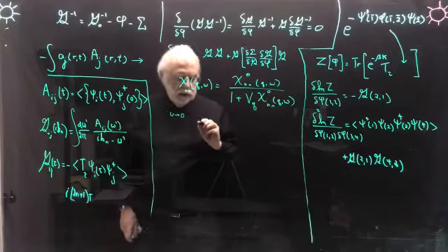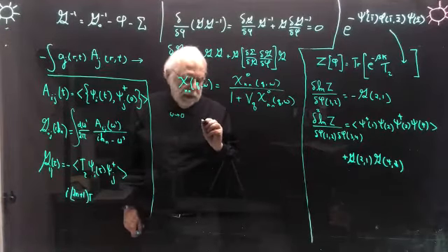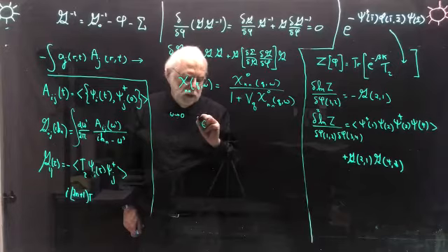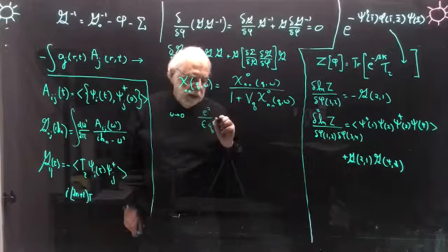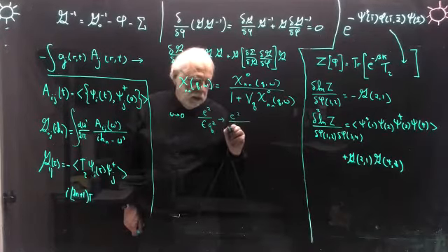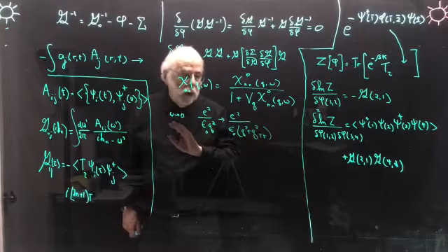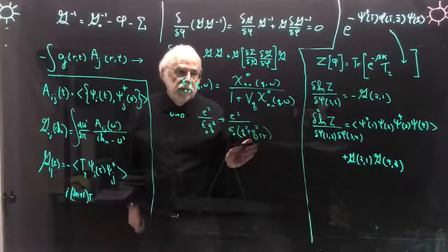So the dielectric constant will be such that epsilon v of q, which is related to e squared over q squared epsilon, will go to e squared times, here it was epsilon_0, q squared plus q squared Thomas-Fermi. So as omega is small, we have screening.